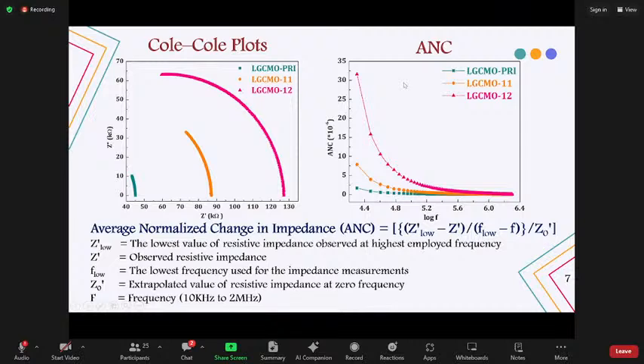From the graph, we can see that the grain boundaries and grains play significant roles in governing the electrical properties, whereas competitive effects of grain boundaries and grains can be realized in the intermediate frequency region. From this, we can see that there exists a sharp change at the higher and lower frequency regions, where ANC is sharply decreasing, so it can be calculated at the intermediate frequency region, where ANC varies insignificantly with frequency.